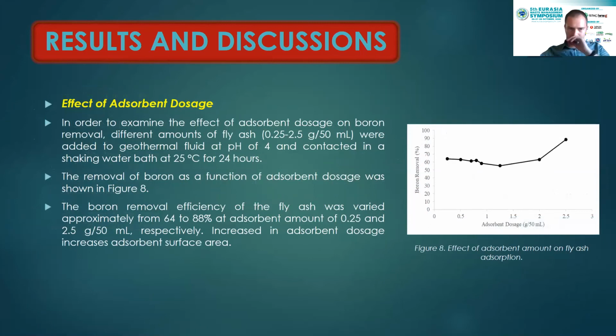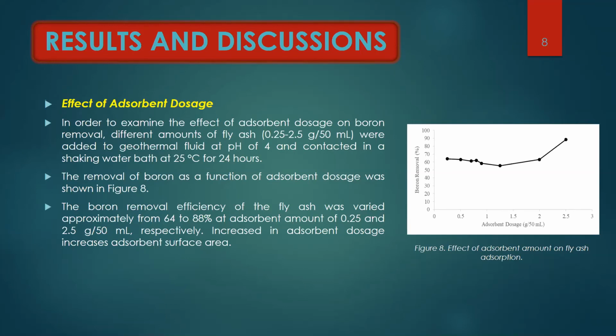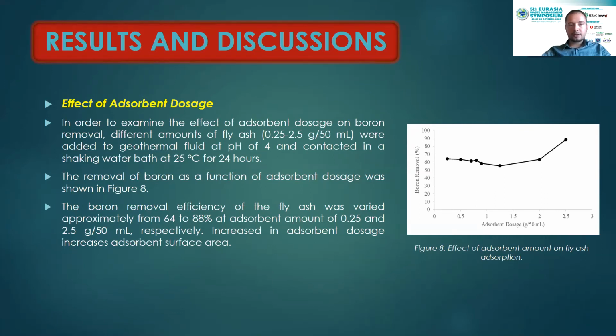Effect of adsorbent dosage. In order to examine the effect of adsorbent dosage on boron removal, different amounts of fly ash were added to geothermal fluid at pH of 4 and contacted in a shaking water bath at 25 Celsius for 24 hours. The removal of boron as a function of adsorbent dosage was shown in figure 8. The boron removal efficiency of the fly ash varied approximately from 64 to 88 percent at the adsorbent amounts of 0.25 and 2.5 gram per 50 ml, respectively. Increase in adsorbent dosage increases adsorbent surface area.